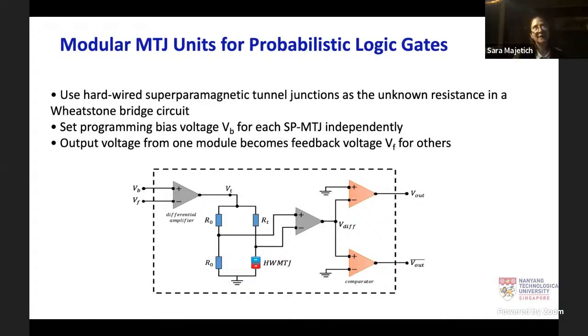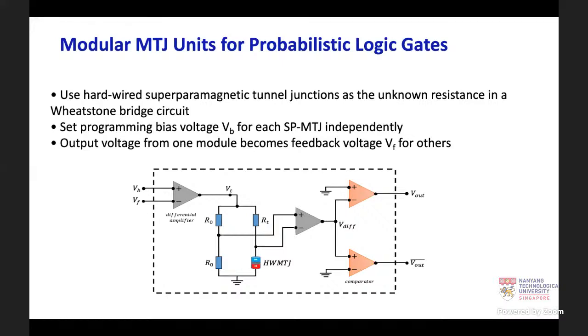We're typically getting overall like 1.5 kiloohms. And that's with a tunnel barrier more than a nanometer thick, but less than 2. If you get above 2, then for the kind of diameters that we're interested in, the resistance starts shooting up. But I think what's really more important is getting those good interfaces with the CoFeB, when you anneal it so that you get the spin filtering effect and reasonable TMR.